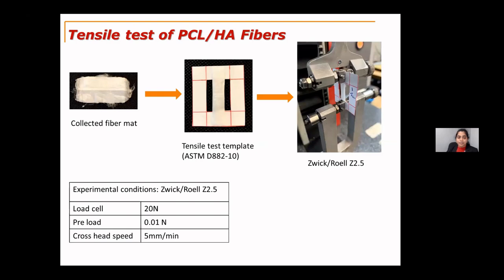And after that, we did a tensile test for the fibers. Tensile testing is not mostly done for nanofibrous mats, because these fibers are not properly oriented and it might not give consistent results. But we chose a consistent method, and we tried to be accurate in everything we considered here, and we did the tensile test for these fibrous mats. We followed ASTM D882 standards to do this tensile test.